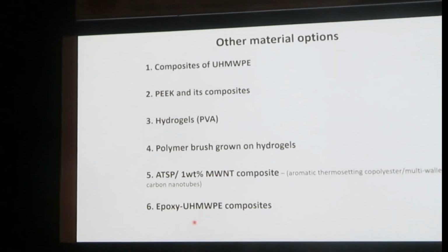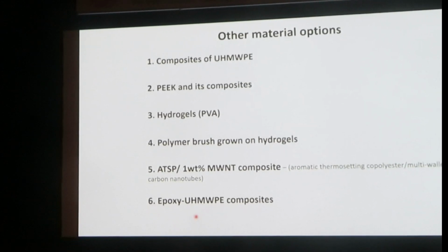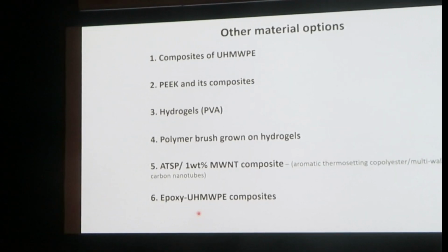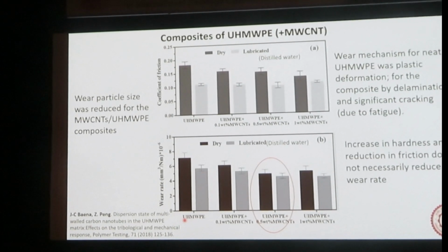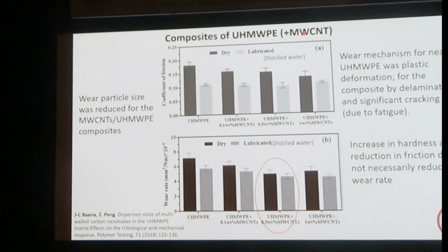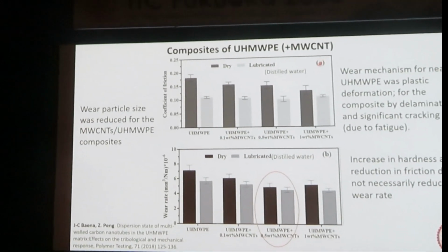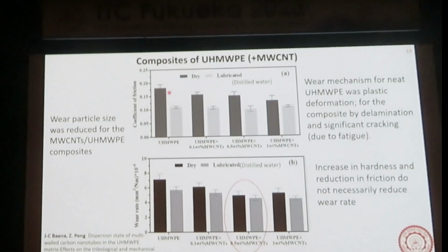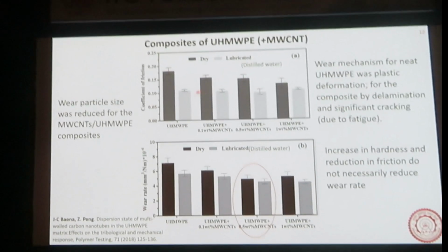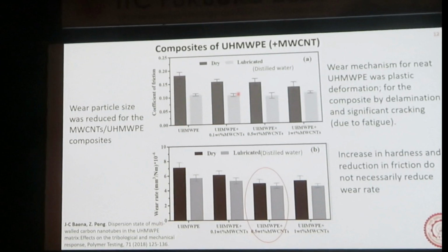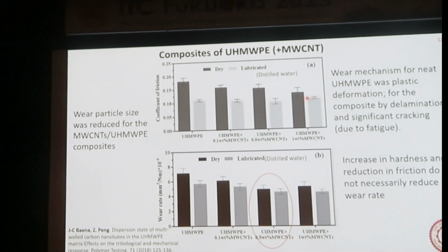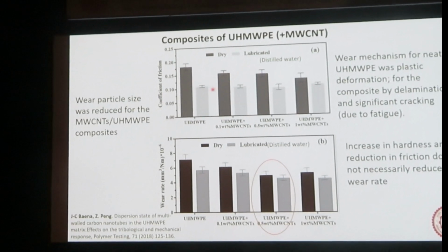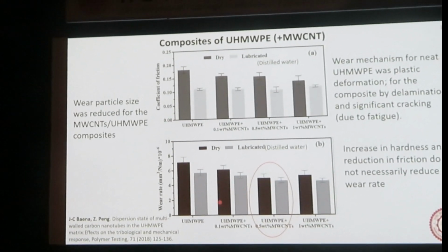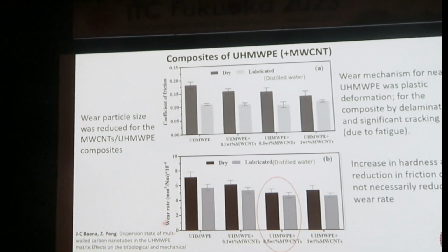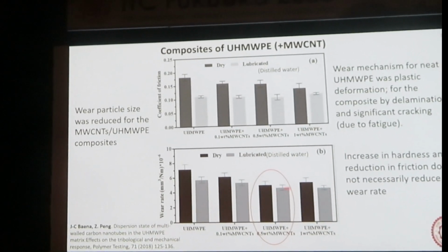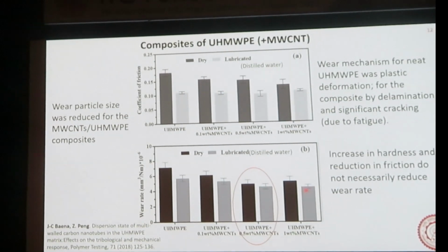And then our solutions: we have worked with epoxy UHMWPE composites. So let me just review some of the literature. First, composites of UHMWPE with multi-wall CNT. In both dry and lubricated conditions, especially in dry cases, you can see a lot of reduction in the coefficient of friction, but in the lubricated case, there is not much help. But in the case of wear, this is the wear rate here, and the wear reduces for the lubricated condition